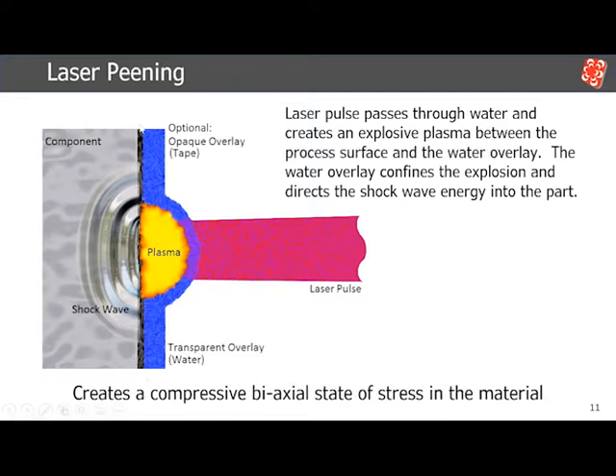One optional overlay is the opaque overlay. Historically speaking, a lot of the applications were around titanium, and opaque overlays are used to prevent the plasma interaction with the material. For titanium, that gives rise to alpha case, which is detrimental for the process. That being said, most of our processing no longer includes any opaque overlays except for titanium.